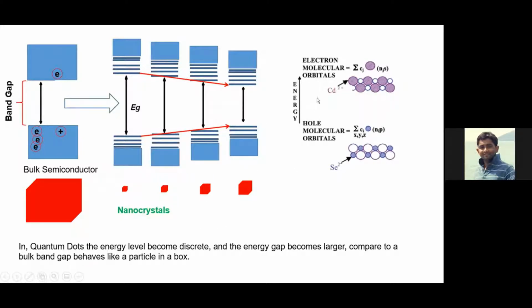And interestingly, take for example cadmium selenide. As selenide is full of electrons, it generally forms the valence band of the nanocrystals, and cadmium 2 plus generally forms the conduction band of the crystals. And as selenium is full of electrons, it does not move very well, but the conduction band is an empty orbital, so it moves drastically, and the band gap tuning depends only on the conduction band. And by this tuning you can get different types of quantum dots.